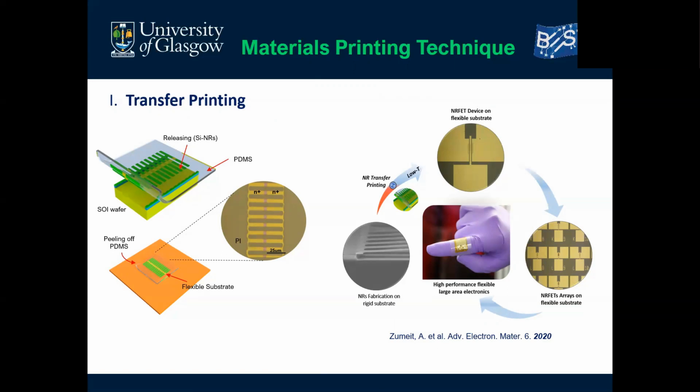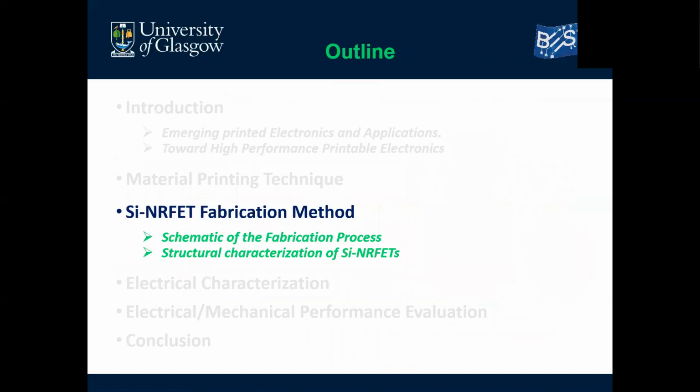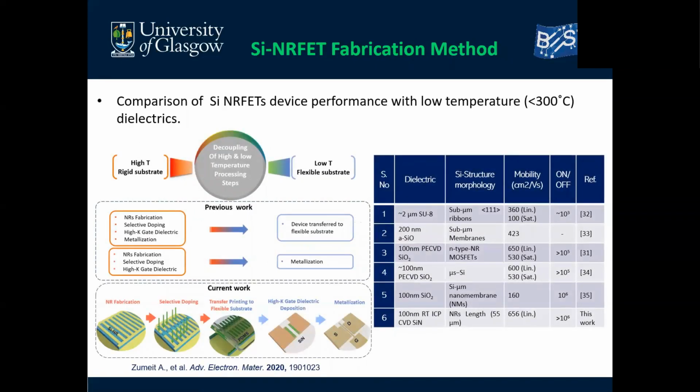A major challenge with nanostructure based devices is that some of the critical fabrication steps, for instance, doping and high-k dielectric deposition, require high temperatures that are incompatible with flexible substrates. Therefore, it's important to develop device fabrication strategies such that all the fabrication steps are carried out at low temperature. So here, since the high temperature fabrication steps are carried out before the transfer printing, this method we use decouples the high temperature process steps from the low temperature steps. And all the steps that are carried out after transfer printing realize a device on the flexible substrate,